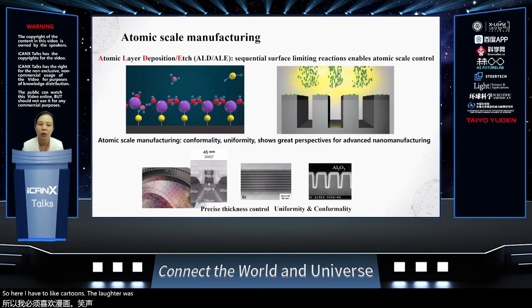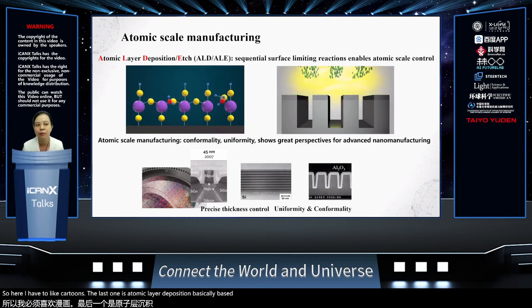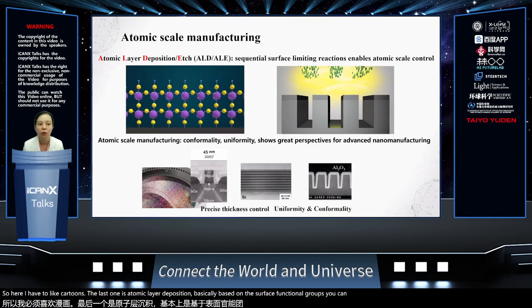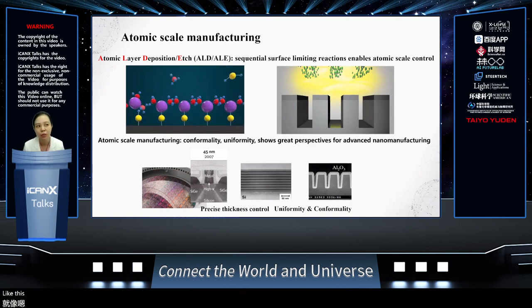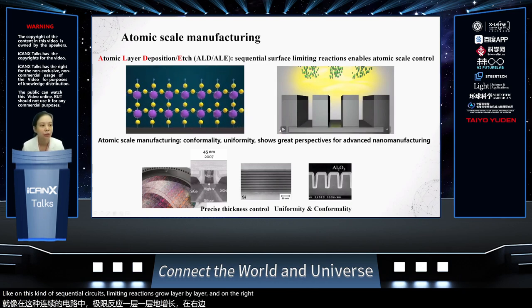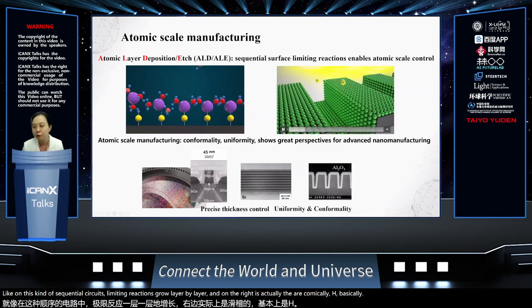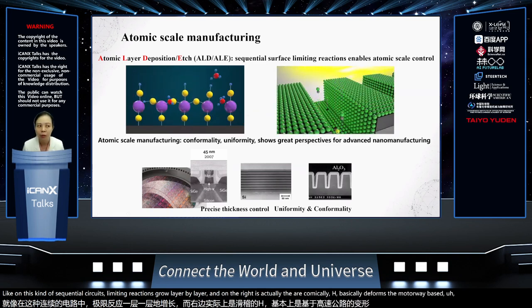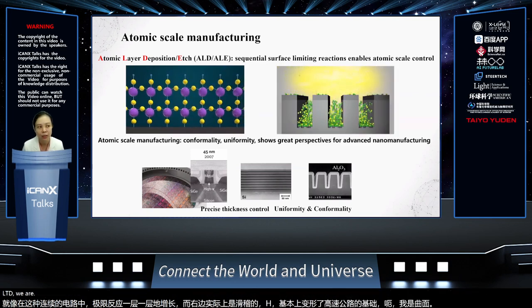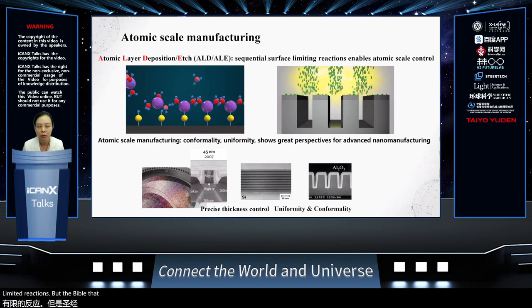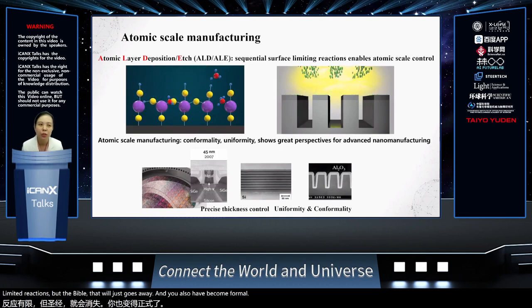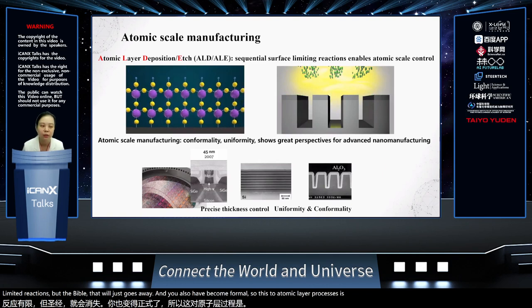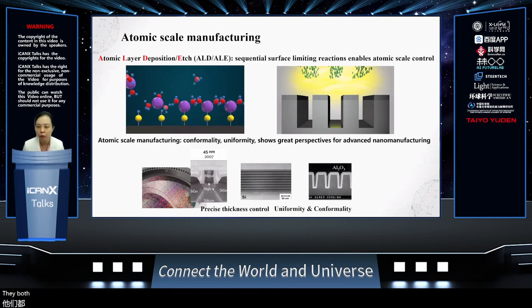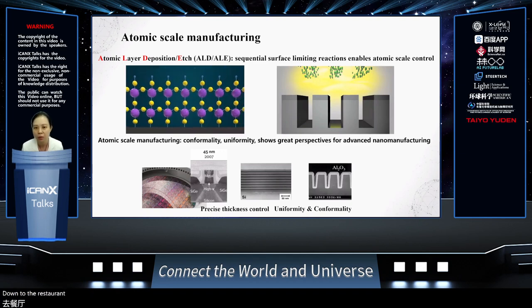The left one is atomic layer deposition. Basically, based on the surface functional groups, you can grow this kind of sequential surface-limiting reactions layer by layer. And on the right is the atomic layer etching. Basically, they work in a similar way, you form surface-limited reactions, but the byproduct will just go away, and you also have the conformal. So these two atomic layer processes share some similarities. They are both conformal, uniform, and you can control them down to the angstrom scales.